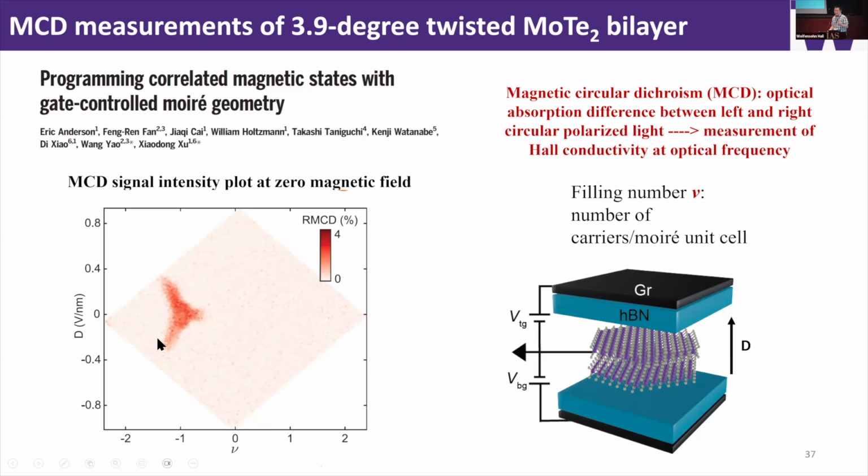I want to emphasize that this MoTe2 itself is a semiconductor, it's non-magnetic. It just doesn't give you this magnetism. But what we do here is we have a moiré system. We create a moiré with a twist angle, and this particular sample is about 4 degrees-ish, 3.94 degrees.